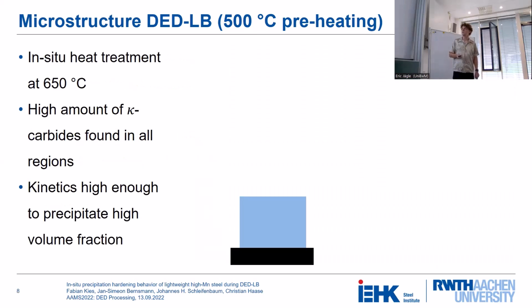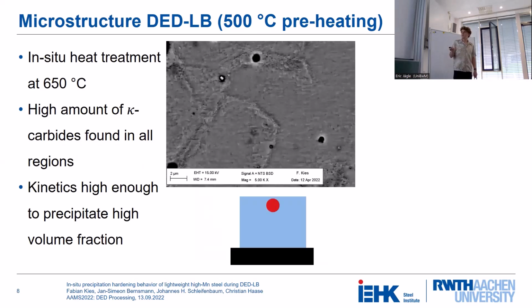But if we increase the preheating temperature to 500 degrees C, our process takes place at around 650 degrees C. And there we can see kappa-carbide precipitation. So first, a microstructure on top of the sample, which means this position has seen a low amount of heat. And there you can see, this is not noise, this is etching of the kappa-carbide phase in the manganese-poor regions, but you see a higher volume fraction in the manganese-rich regions.